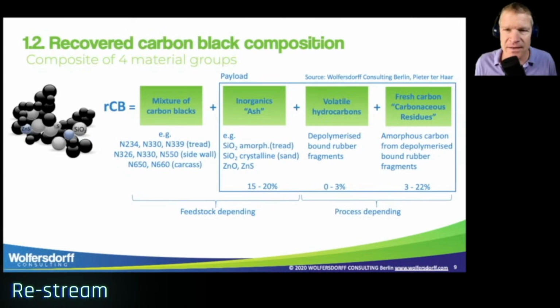The 3 other groups we get, I call them a payload, because we get them because these materials are also in the tire or are produced by the process. The second group is the group of inorganics, also called ash. This could be amorphous silica from the fillers in the tread. In Europe, there is a lot of silica filler in the tread. It could also be crystalline silica. This is not so good. This could come from sand in the profile of the tire. So we have to clean the tires not to have the crystalline sand, because when we mill the recovered carbon black to below 10 micron, this will become respirable crystalline silica, which is considered a dangerous material.